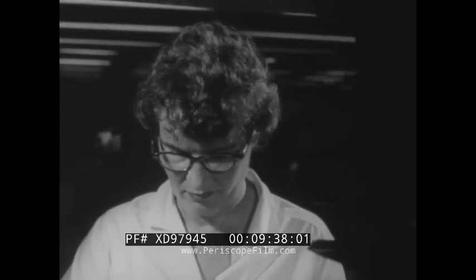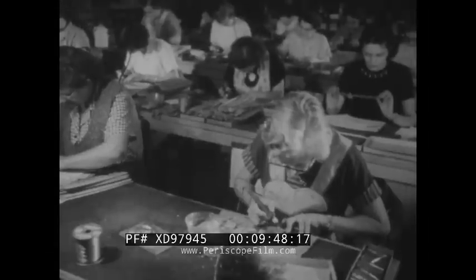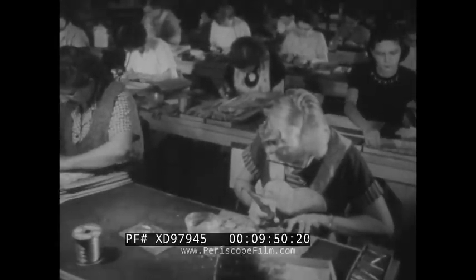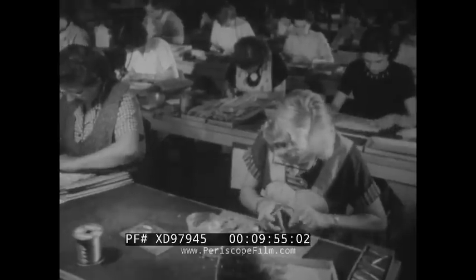Even more interesting than the application of the methods of the potter's trade is the use of the printer's techniques as well. Here on little ceramic base plates, an electronic circuit is actually being printed in silver paint. On each tiny rectangle is printed a complex setup of capacitors, resistors, wiring, the works. After a trip through the oven to convert the silver paint back into solid metal, leads are attached and soldered firmly in place.